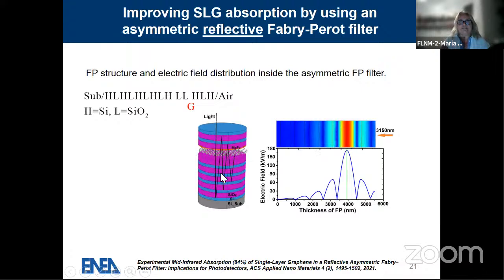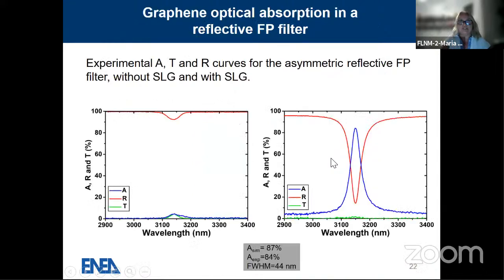We have further increased the reflectance of the bottom mirror. Here we have got only 1 position. We can see the experimental results here showing 84% of absorption against the 87% that we obtained by simulation.